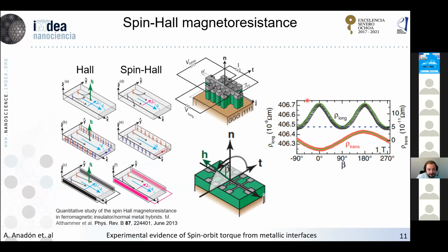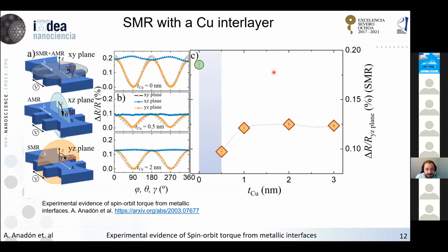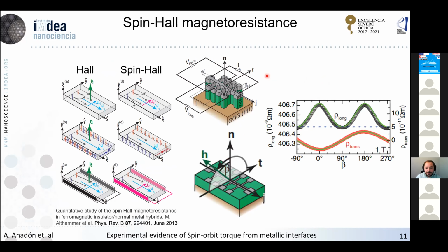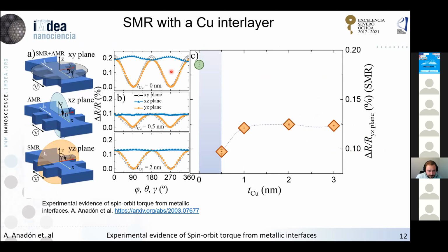And basically, we have, as he said, two states of higher and lower resistance depending on the orientation of the spins in the upper and bottom layer. And this difference basically gives us information on how the system is now. So we made a spin-Hall magnetoresistance measurement with dependence on the thickness of the copper interlayer. What we observe here is that in the symmetric platinum cobalt platinum layer, we have a rather high spin-Hall magnetoresistance, but as soon as we introduce the copper interlayer, this is drastically reduced.